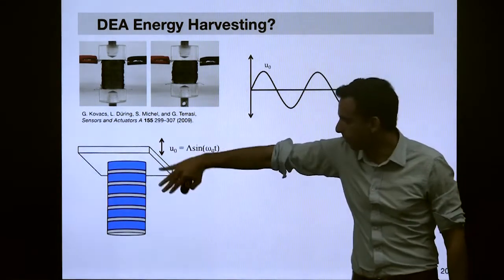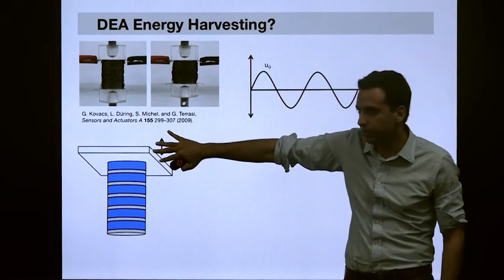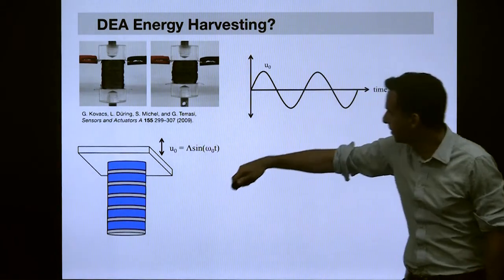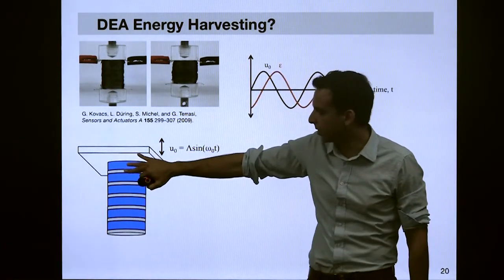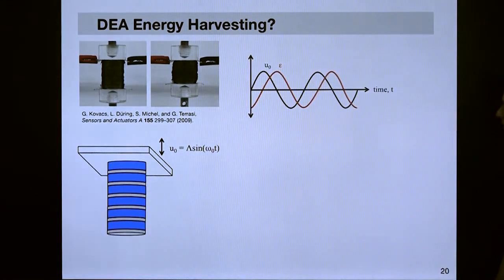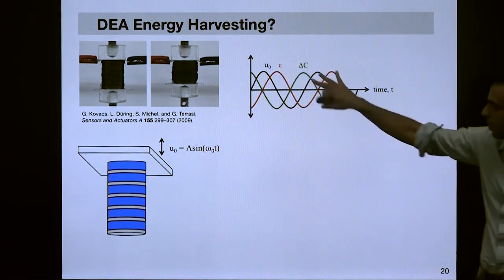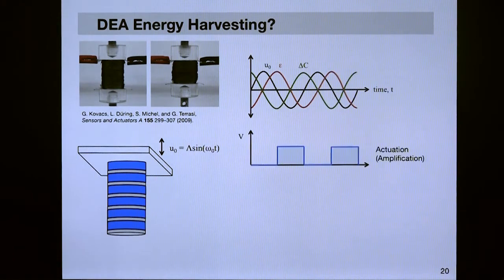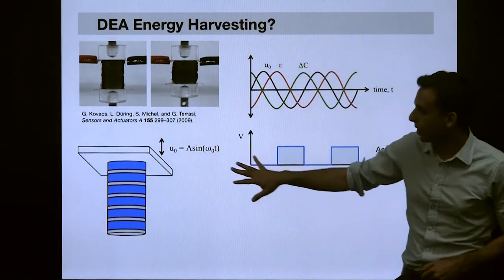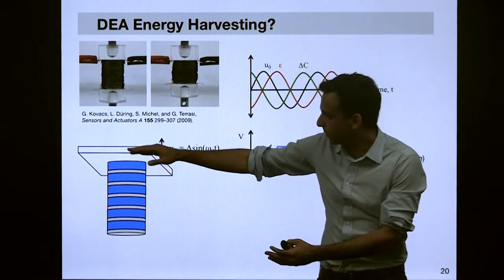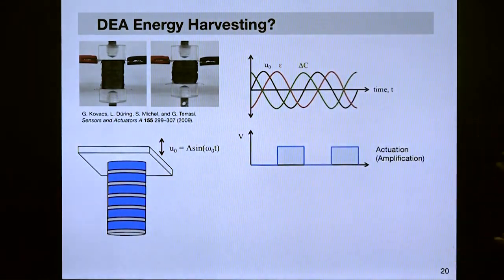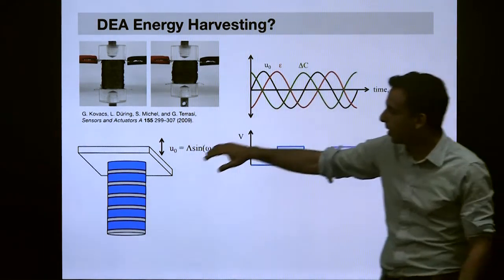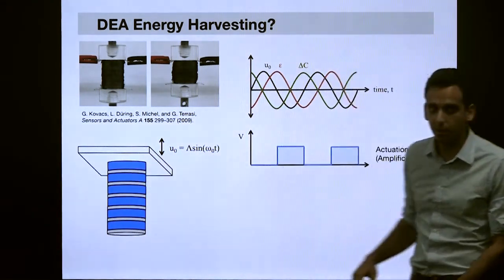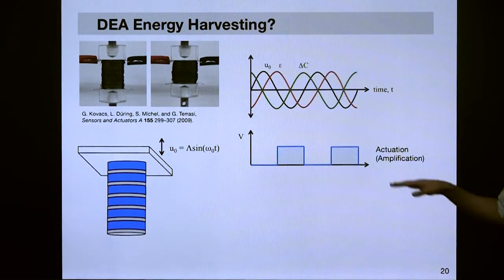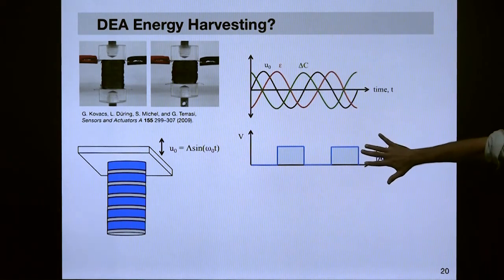If you apply some harmonic excitation to this through your building, you get displacement at the base. That corresponds to 90-degree out-of-phase strains in each of these capacitive elements, and then we can calculate the corresponding changes in capacitance. There are two modes of operation. As we apply this harmonic oscillation and get periodic compression in these capacitive elements, at those moments of compression we could amplify the compression by applying electric voltage.